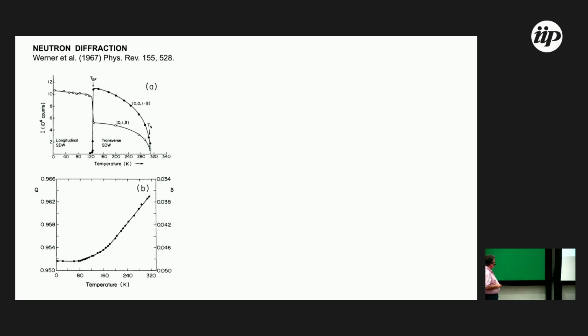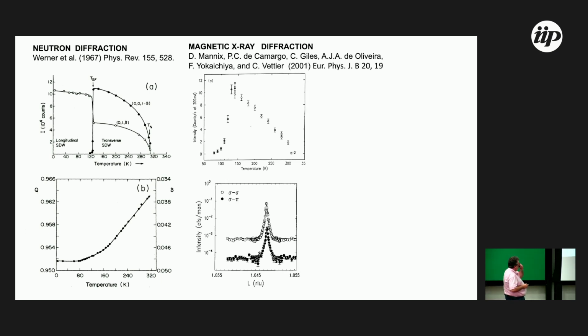And here we observe the size of the Q. The wave vector is 2π/a (1 minus delta), for example. The change in the size of delta is observed as a function of the temperature. I know this technique, but the Néel transition of chromium, at 311 K, is a high temperature. So the delta is approximately 4% of the lattice parameter. And this experiment was performed at ESRF in 2001, by me and my collaborators, observing X-ray diffraction of the spin density wave.